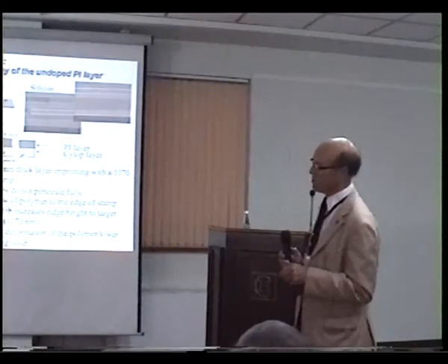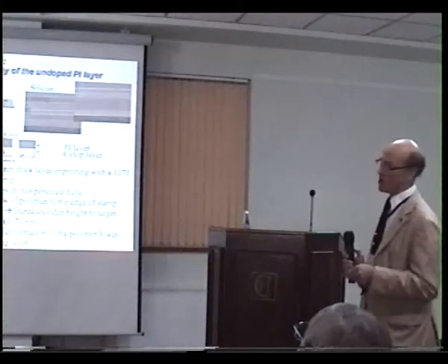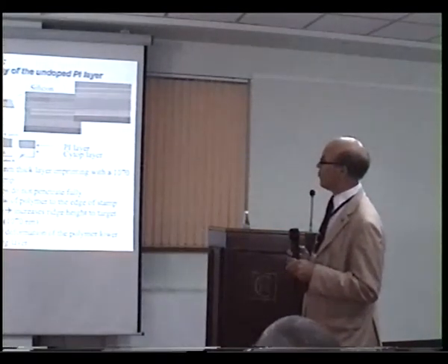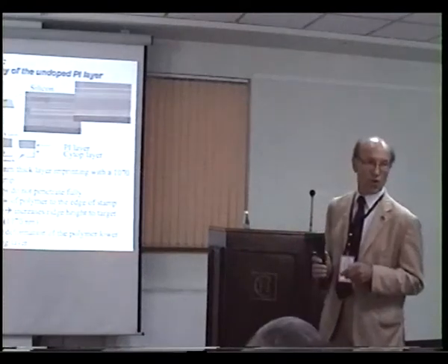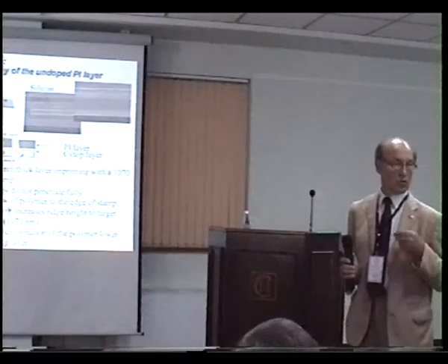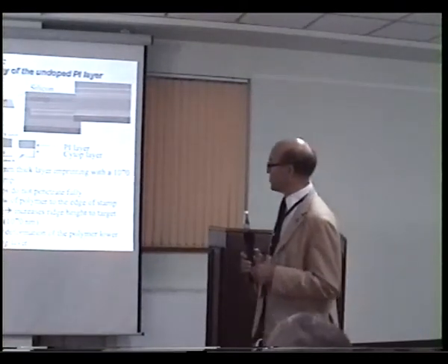And we can go to depths as deep as 1 micrometer, which is the requirement in this case. So this is an application of nano-imprint lithography where the polymer that we're deforming is the polymer from which we are making our device. It is the polymer in which we're going to propagate light. Light in the infrared at a wavelength of about 1.3 micrometers.